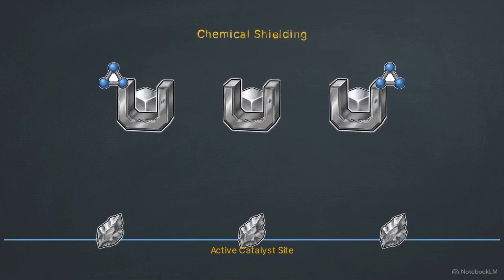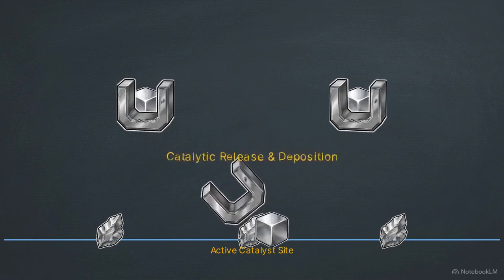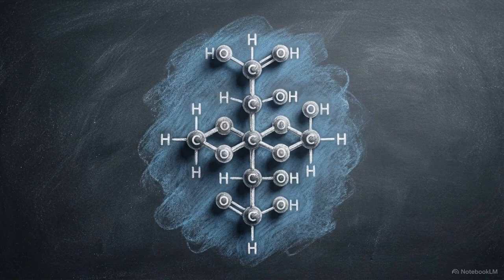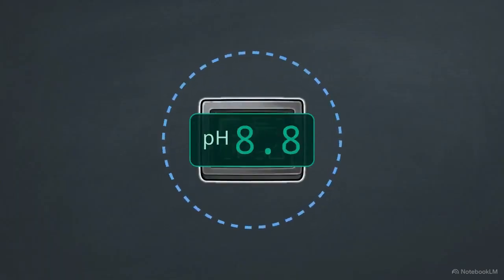D-gluconate ions act as a chemical leash, limiting free ion concentration. The ligand only releases its grip upon physical contact with the active surface, strictly bottlenecking the deposition rate. D-gluconate also performs a secondary, equally vital function. It buffers the pH of the bath.